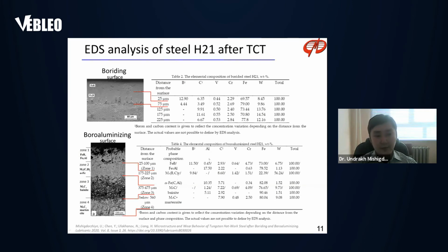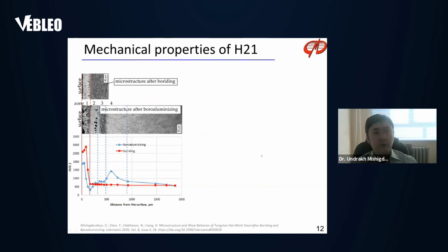And we can also see how aluminum diffuses. It diffuses at most up to zone 3, and its maximum concentration there is 5.11%. Boriding provided high microhardness, up to 2900 HV. This is actually quite high, probably due to alloying of the boride layer with tungsten, chromium, and vanadium. Then in the transition zone, microhardness values drastically dropped to around 600 HV and remained fairly flat.